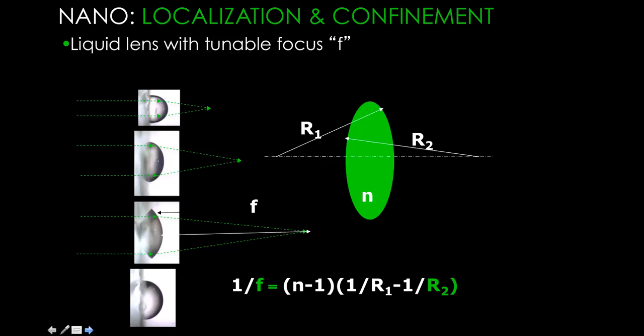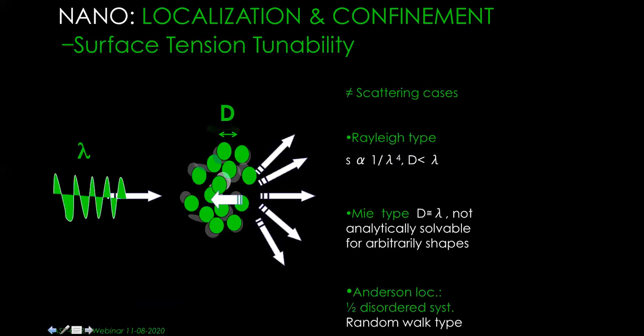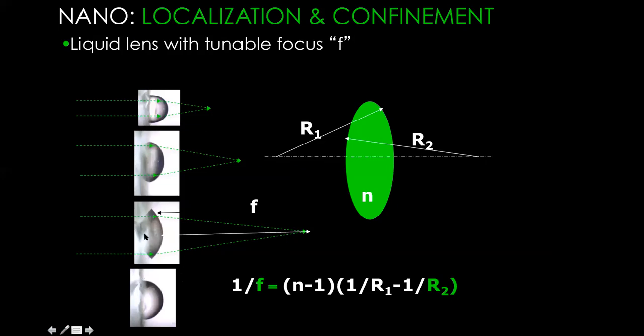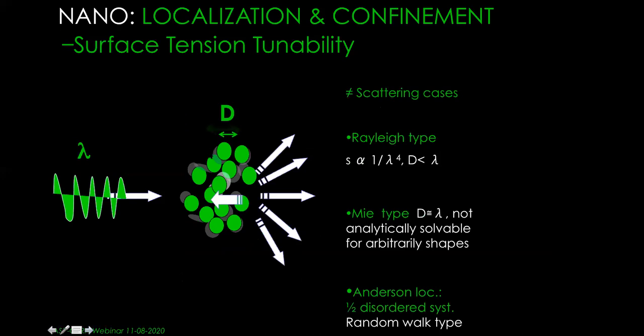Again, the aim of Dr. Balangom at that time was to make a liquid optical lens, with a controllable focus, tunable by light. This would allow a number of applications that I should not discuss, but unfortunately, it has not worked. Why? Because the surface at the bottom here, which is zinc oxide nanorods, diffuses light extensively. So we have to optimize the size and the distance between the nanoparticles to minimize this scattering.